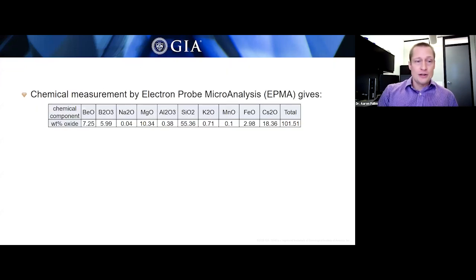Now, the next step, though, we had to do some chemical analysis. So if you're going to describe a mineral, Evan touched on this as well, you need both the structure and the chemistry. And so we turned to electron probe microanalysis in order to measure the chemistry of this stone. And what we found was that the chemistry is obviously very different from what you expect for beryl. So in this case, we have a lot of magnesium, we have some boron in there. We're missing that aluminum that you expect to see in beryl. And so this is the result that we got from the electron probe microanalysis.